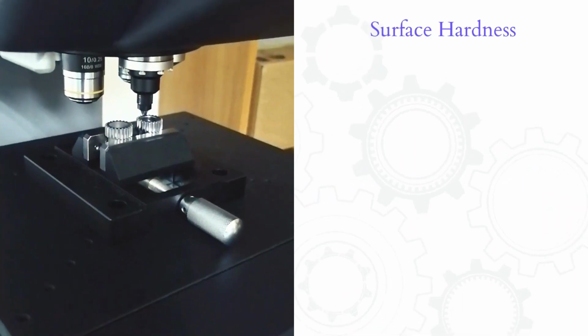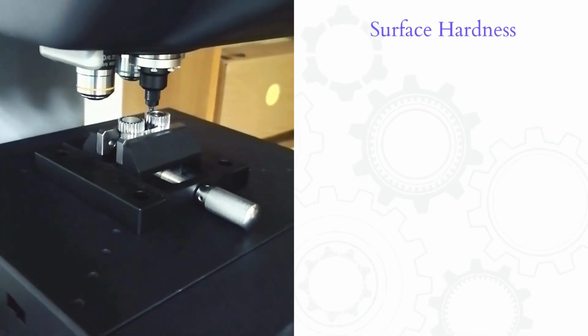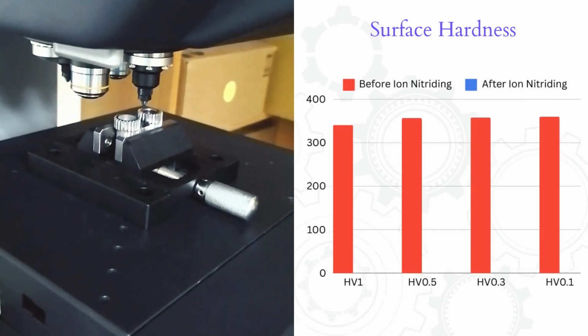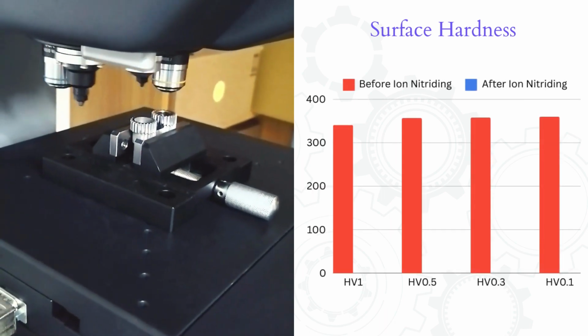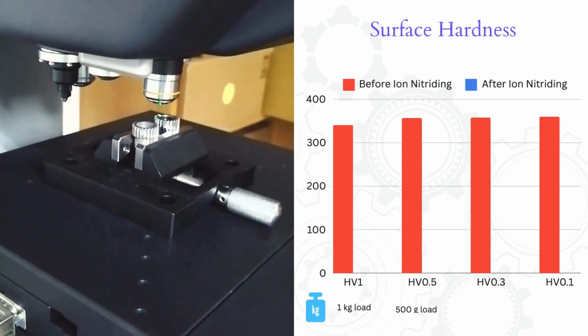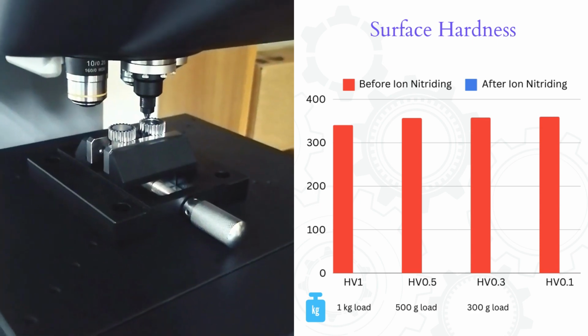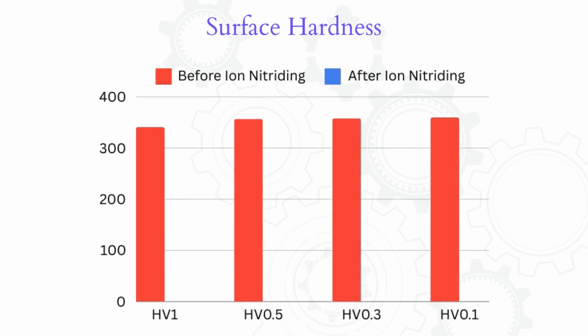Okay, let's start by measuring the surface hardness before nitriding. We will be using a Vickers hardness tester, and we will use the loads of 1 kilogram, 500 grams, 300 grams, and 100 grams. We will come back to why we are using these loads later. We measure a few times with each different load, and then we give the average for each.